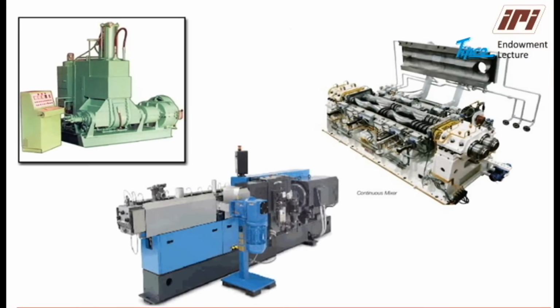You can see on the extreme left, there's an intensive batch mixer or a Banbury type mixer. On the right, you can see a continuous mixer. And on the bottom, you'll see the workhorse of master batch manufacturing. That's a twin screw extruder. Most of the master batchers use twin screw extruders to get good outputs and a whole range of possibilities when it comes to materials, because twin screws are very versatile for most materials, starting from your basic polyethylenes to your polyether ether ketones.